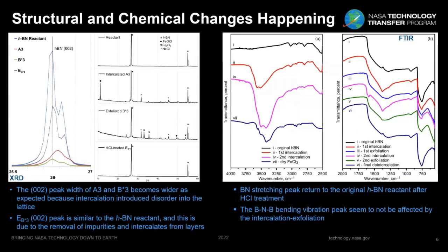Sorry. In the FTIR spectra on the right side, you see all the chemical changes happening in the boron nitride. You can see it going from the normal hBN peaks, the black line on the top, through two processes of intercalation and exfoliation, and then back to the clean sample after being exfoliated and cleaned by HCl. You see the peak is back to normal, like the original sample. All these changes you see in the stretching band around the 1300 peak, the BN stretching, but on the other side, the BNB, sorry, vibration bending peaks, you don't see that many changes. You don't see any visible change. So the changes are happening in the stretching band.